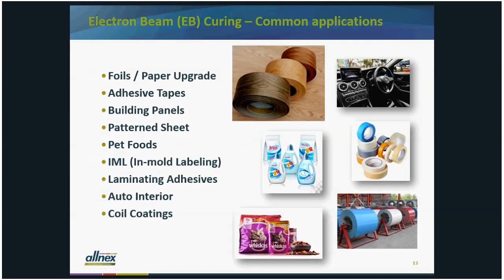Tapes, building panels, we've seen pattern sheets where you have a pattern on a film that could be transferred to the surface of your coating, and you can cure through that film with electron beam, whereas you might not be able to do the same with UV. Electron beam is also finding inroads in in-mold labeling, laminated adhesives, as we've mentioned 2 or 3 times already, auto interior coatings, and it has been looked at for quite a while now in coil coatings.